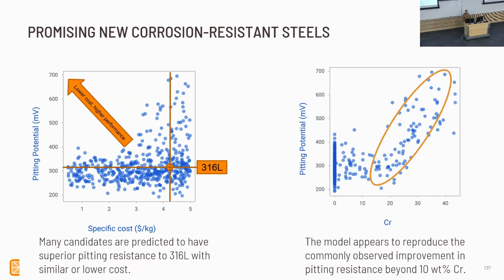And so we actually started looking at some of these with our collaborators at Ohio State to maybe melt some and just test to see if they were agreeing, at least notionally, with this machine learning prediction. The plot on the right is interesting because with any of these kinds of machine learning predictions, you want to understand: does it make physical sense? Is it consistent with my intuition or prior history with these materials? Pitting potential is a very common metric for stainless steels. The higher, the better. That means it's more resistant to corrosion and exposure to water.